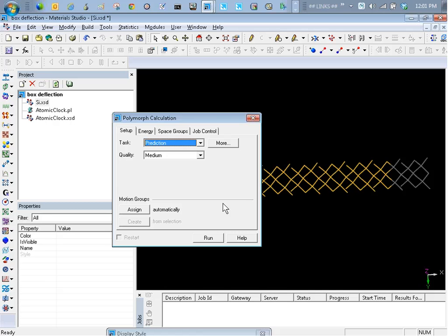This approach, right, and there are a variety of extensions and modifications to this, at its core requires the development of good intra and intermolecular potentials, right, and charge distribution schemes. You then do a Monte Carlo packing type approach if you know nothing about the crystal structure, and that allows you to construct different configurations, subject to symmetry or not subject to symmetry, in different symmetry space groups, to then do a Monte Carlo temperature ramp up. So basically you heat it up till it becomes a very low density system, and then you cool it down till it starts to crystallize, i.e. coalesce, i.e. the density starts to increase. You then accept a series of these and then apply full force field minimization to those. You then take those and save them, and then you can run them with Materials Studio script through a range of different quantum mechanical prediction algorithms to put them on a common basis across multiple space groups and multiple areas.